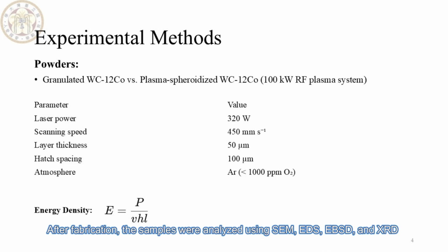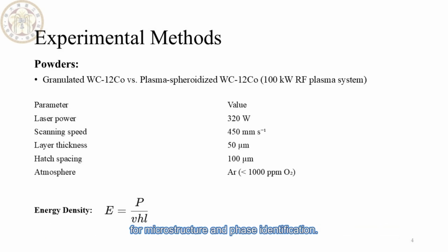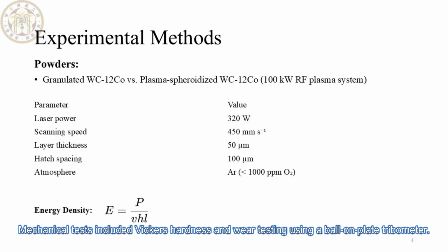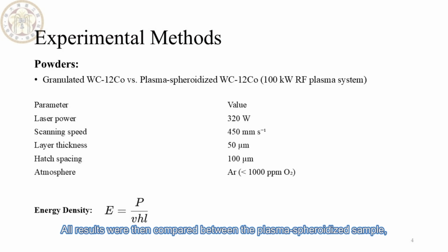After fabrication, the samples were analyzed using SEM, EDS, EBSD, and XRD for microstructure and phase identification. Mechanical tests included Vickers hardness and wear testing using a ball-on-plate tribometer. All results were then compared between the plasma spheroidized sample, called sample S, and the granulated powder sample, sample G.